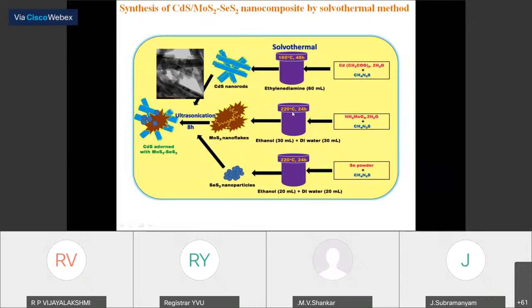Here it is 220 degrees and 24 hours. Here they also use 220 degrees and 24 hours. So like that, by maintaining different temperature and time, we obtain the nanorods, nano flakes and the powder. So like this, we obtain 3 compounds.